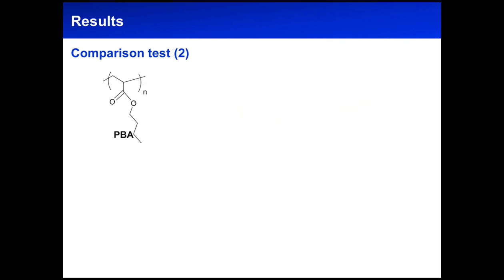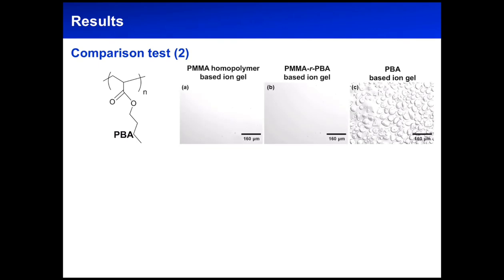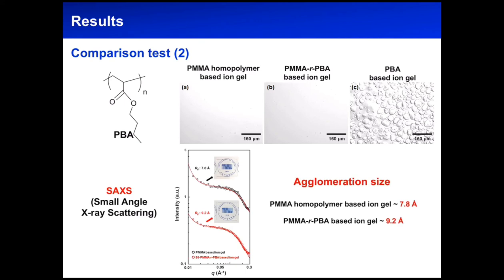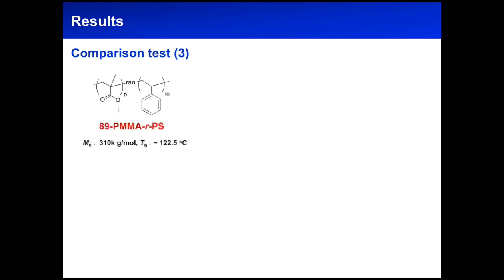However, as the DSC data and stress-strain curves show, the stretchability is not affected by the glass transition temperature. So, we compared the solubility of each polymer domain in ionic liquid. In these microscopic images, the PMMA homopolymer and PMMA random PBA copolymer could be made into a homogeneously mixed gel system, except the PBA homopolymer-based ion gel. Moreover, in the SAXS data, we can extract the size of the insoluble domains in ion gel. Compared with the PMMA homopolymer-based ion gel, PMMA random PBA-based ion gel has larger agglomerates, which means that the PBA domain is not dissolved in ionic liquid. So, we finally assume that the ionic liquid insoluble PBA domain, which has a low glass transition temperature, is the crucial factor for ion gel stretching process.